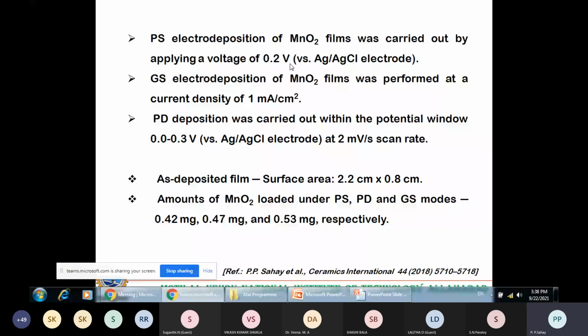In the case of galvanostatic electrodeposition, the current density was 1 milliampere per centimeter square. In the case of potentiodynamic deposition, it was carried out with a potential window of 0 to 0.3 volt, at 2 millivolt per second scan rate. So all these process parameters have been optimized: 0.2 volt, 1 milliampere, 2 millivolt per second and the window. These are the optimized parameters which we are quoting here.